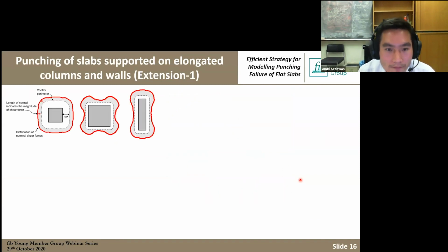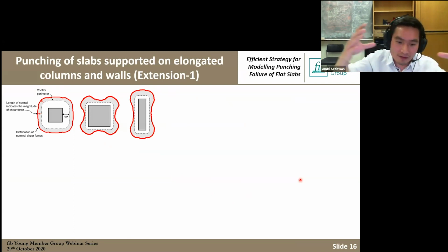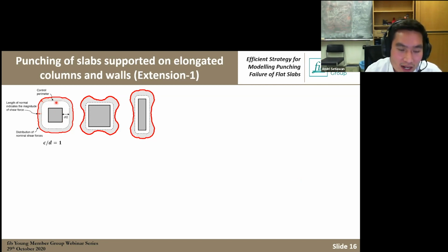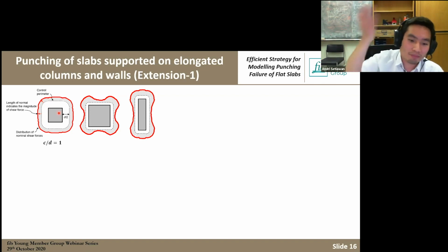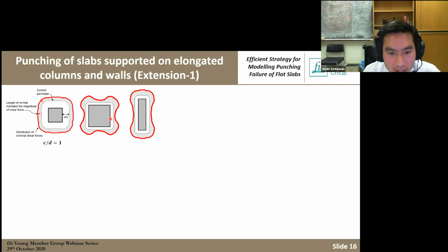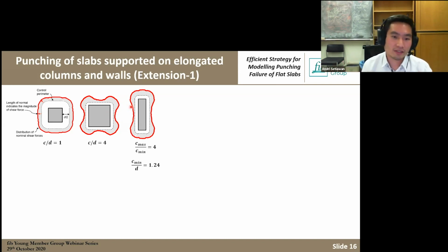So for the extension to slabs supported on columns and walls, the difference is that when you start having a rectangular or long column, the shear stress becomes less and less uniform. You can see in here, the left figure is a typical scenario where C is the column size and D is the effective depth of the slab, and they are equal. This represents a uniform stress that is typically modeled in the previous stage of the verification. And we are moving to the right part where we have a larger square column or an elongated column, where you can see that the shear stress concentrates more on the corner region and a minimum shear is carried by the middle region.